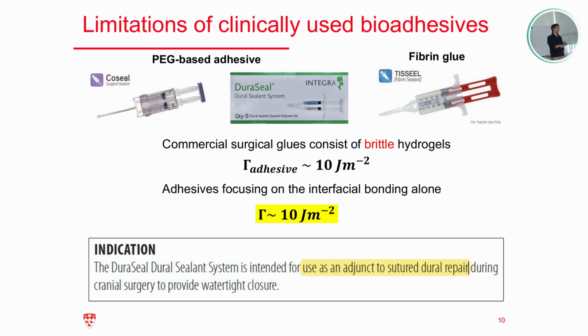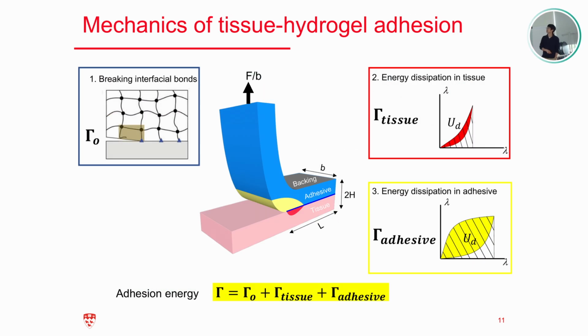Because of that, the manufacturers already recognize this limitation, and they clearly indicate, as you can see, that this product, the DuraSeal dural sealant system and the hydrogel glue, can only be used as adjuncts to the suture. It cannot be used alone because of the weak adhesion and the weak mechanical property. So how can we understand, how can we engineer better bioadhesives?